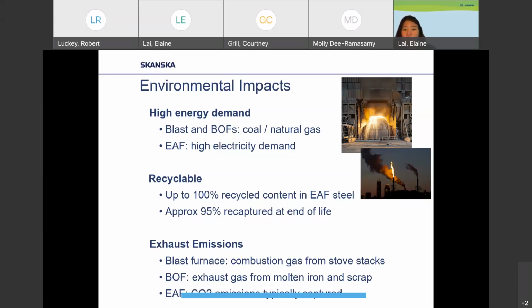The amount of CO2 emissions per ton of crude steel from the BOF and EAF steelmaking on average, if you're comparing the two, the basic oxygen furnace, or BOF, on average is about 1,149 kilograms of CO2 per ton, versus the EAF is about 470 kilograms of CO2, so a little less than half.